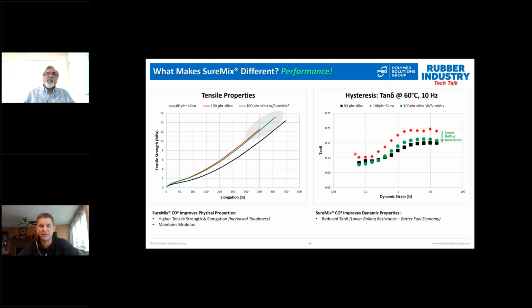And of course, here on the right, the main thing that everybody looks at, right? What is the hysteresis? When you're talking about silica dispersion, the expectation is a reduction in hysteresis. Here, going from the black curve to the red curve, you see that increase in hysteresis that Ricky mentioned. That comes from the challenge of getting the dispersion of that extra silica. Using SureMix in this compound, we're able to take the hysteresis down from the red curve to the green curve. So here we have hysteresis very similar to the 80-part compound.